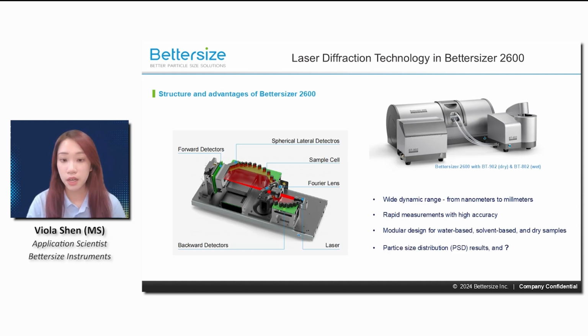So, what instrument can Bettersize provide for laser diffraction technology and particle size analysis? The answer is the Bettersizer 2600. The figure on the left side is our patented optic structure of the laser diffraction particle analyzer. The process begins with sample addition and dispersion to achieve even particle distribution. Then the system collects the scattering spectrum, which is analyzed to produce a particle size distribution result, detailing particle content across specific size ranges. Key advantages of the Bettersizer 2600 include our patented optics, wide measurement range, rapid testing with high accuracy, and modular design suitable for water-based, solvent-based, and even dry samples.